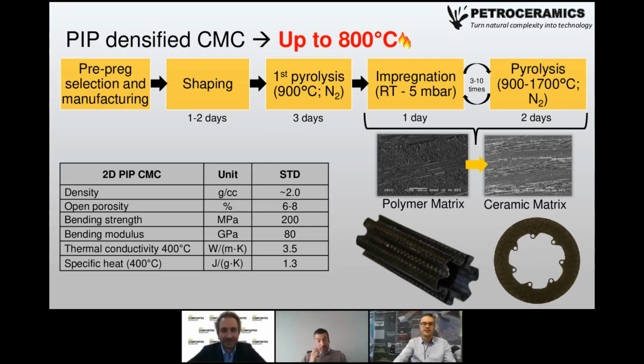So as for PIP densified CMCs, we can handle complex shapes and flat shapes, as you can see from the images in the bottom right. And there are no main restrictions as for the dimension of the objects. So we can perform shaping in compression molding presses or in the autoclave, depending on the shape of the object. And now we have a pyrolysis in order to open porosity and prepare the material for densification. And densification is obtained by means of PIP, so polymer impregnation and pyrolysis. And we can run 3 to 10 cycles of PIP densification, depending on the final density and porosity that is needed for the material. But in the end, as you can see from the SEM images, the polymer matrix will be completely converted into a ceramic matrix.